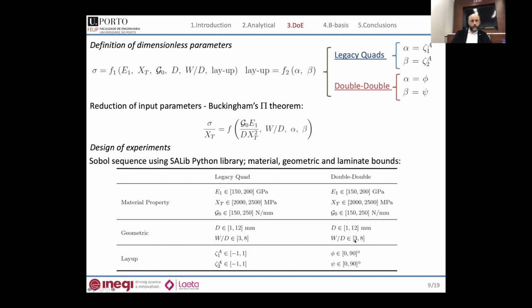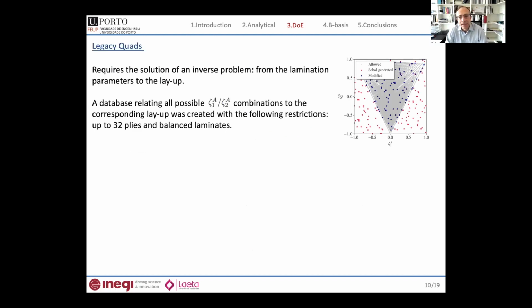Okay, so regarding the legacy quads, like I said, we have to take into account that we have a feasible region, and we have another problem to solve, is that we have to solve the inverse problem. So we need to identify a layup from the lamination parameters, and that can be done with some very complex optimization algorithms. But what we did was just to generate a database that relates lamination parameters with layups, and we do that once, assuming that we have up to 32 plies, and then we just interrogate the database to relate lamination parameters with layups.